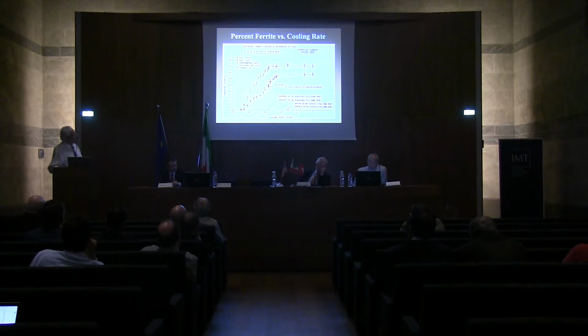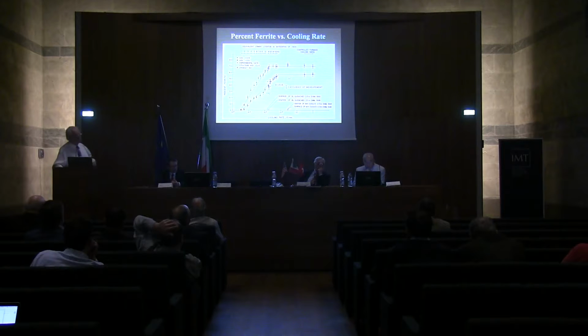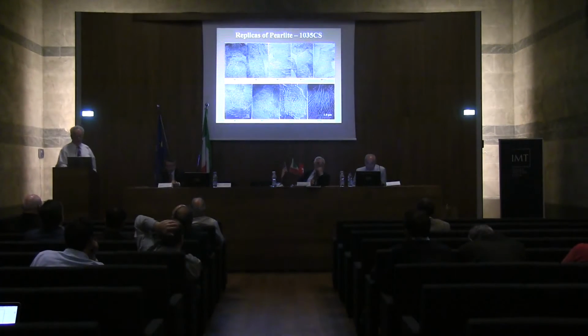Now, I measured the percentage of ferrite as a function of cooling rate, and that's on the y-axis here. The cooling rate in Fahrenheit per minute is on the x-axis. You can see the oil quench results versus the air cooled. With the oil quench, you're down around maybe 25% ferrite. But in the air-cooled, you're up around over 50% ferrite, with the balance being pearlite. So we're using a lot of different approaches to try and prove that the part was really oil-quenched and not air-cooled, as was claimed.